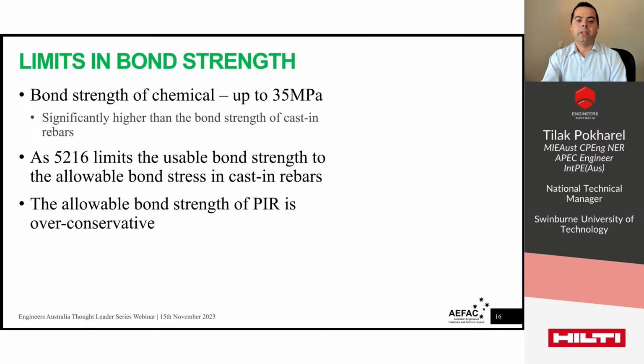Okay, so what is the issue here then? The bond strength of the chemicals we use in connecting post-install rebar is significantly higher than the cast-in equivalent. Okay, but as we just saw, the current rebar model does not utilize the higher bond strength. The limitations in AS5216 were put in place to prevent slip of the rebar under serviceable conditions, to avoid splitting of the concrete, and to address the uncertainty of the unequal distribution of the bond strength over the embedded length. Okay, thus if we had a new model that addresses the slip under the serviceability load, splitting of the concrete, and the variation in stress distribution along the length of the rebar, we could utilize the higher bond strength of the post-installed rebar system.